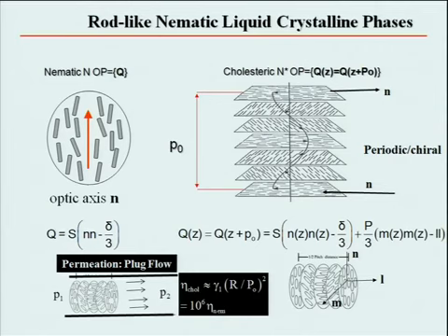And if gamma 1 is a typical rotational viscosity of a nematic, we have a geometric factor here, the radius of the pipe divided by the pitch of this object, which is typically in the micron range. But if you have blue phases, the so-called double twisted phases, they can be sub-micron.